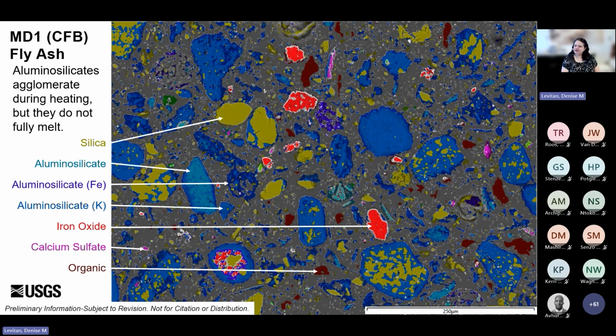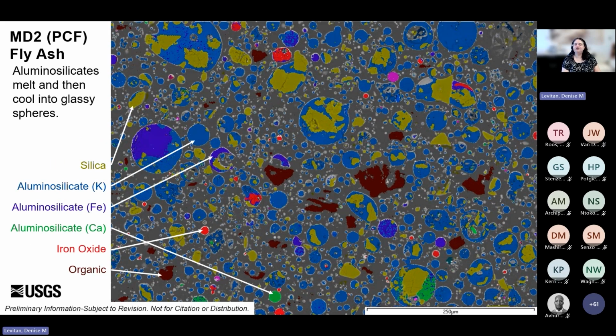So what you can see here is that you have a number of these different particles in different shapes. The silica tends to be these big chunks or agglomeration of chunks with some of the aluminosilicate solids, but distinct minerals with distinct chemistry, or these clumps of minerals, which can happen as the minerals are heated but don't fully melt, then they start to kind of agglomerate. And then we want to contrast this with MD2, the rounded spherical material.